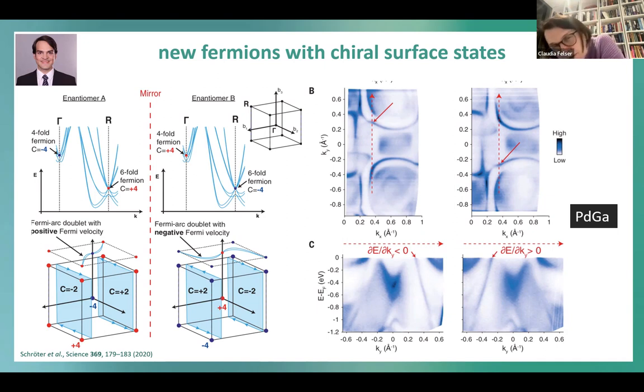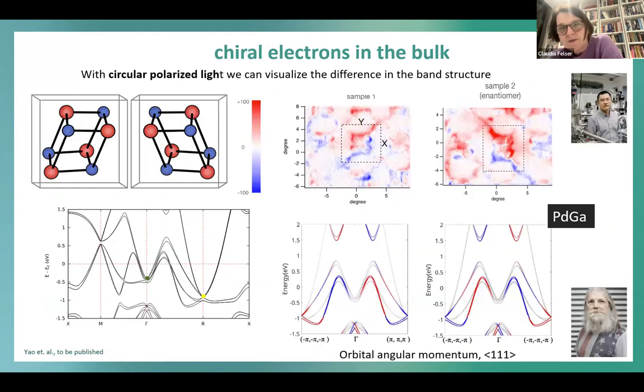And the next slide hopefully shows that we can also have a look at the phase. Exactly. So one way, and this we know from chiral molecules, to distinguish is chiral light. So we thought, okay, maybe it's good if we look at the angle-resolved photoemission data with chiral light. And nicely here, you can really see that the phase is different. If you see here on the right side, the two pictures, enantiomer 1 and enantiomer 2, they also look like mirror images.